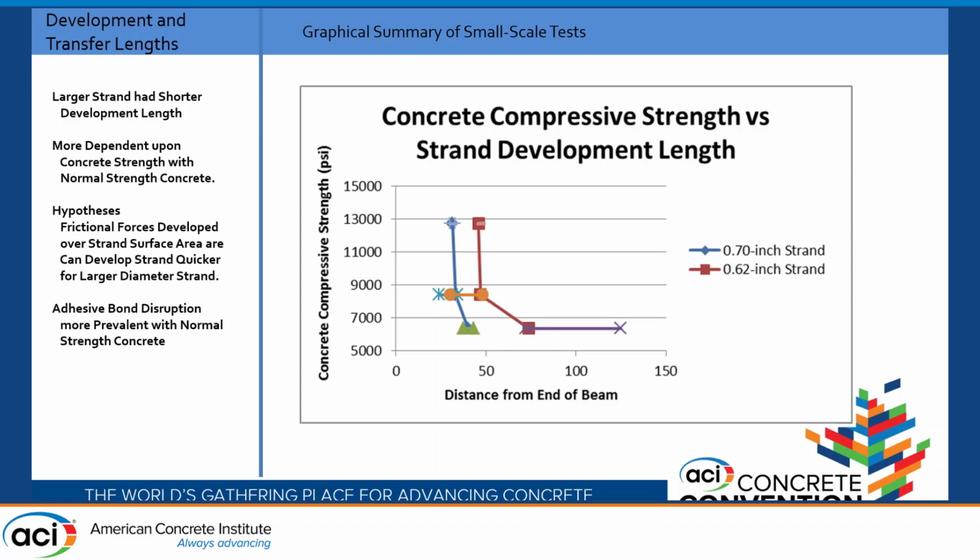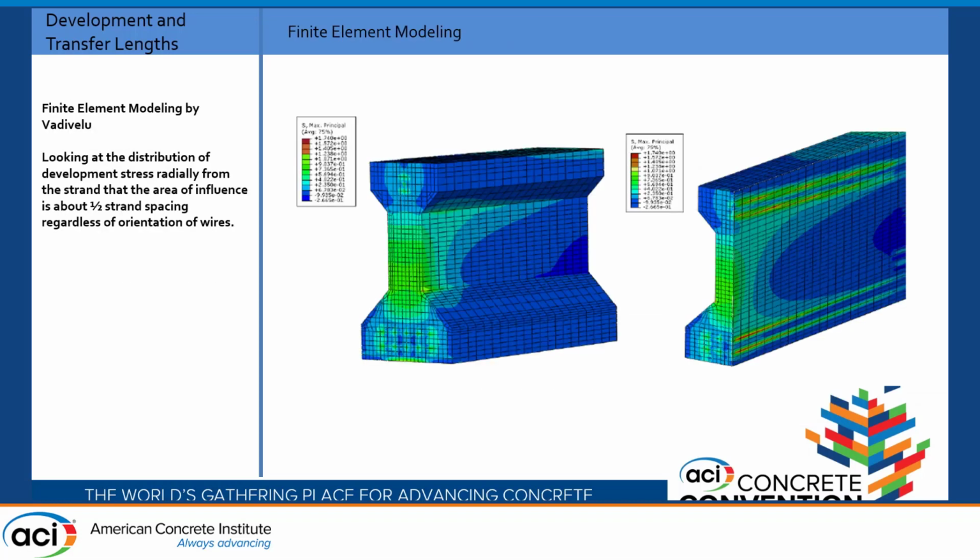length in strands. But as it goes beyond perhaps 8,000 PSI, it's a little bit asymptotic. In other words, there's not that much benefit to it. Some things to remember. So we got thinking about how to develop a model to show this. And so we're thinking about the mechanism of how that strand actually works. You know, there's been a lot of research on it.